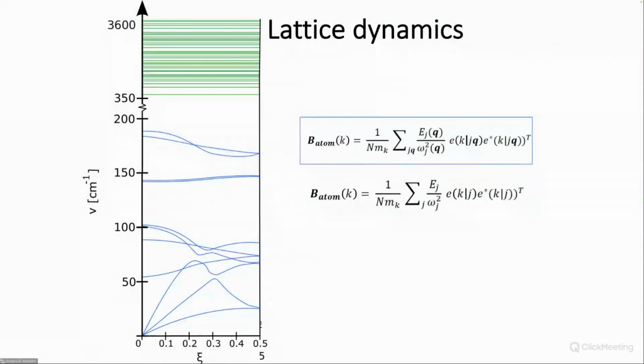So what I just told you was that we could compute the anisotropic displacement parameters by summing up all these lattice dynamical modes of vibration throughout the Brillouin zone. Now, from elastic diffraction measurements, we don't really get information about these phonon dispersions. We only get a mean. This summation will be a mean value over the whole Brillouin zone.